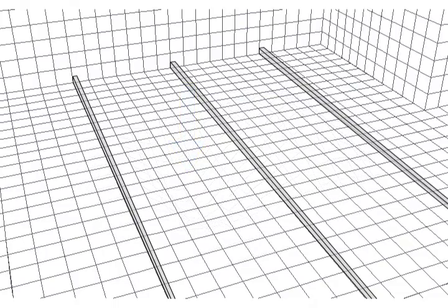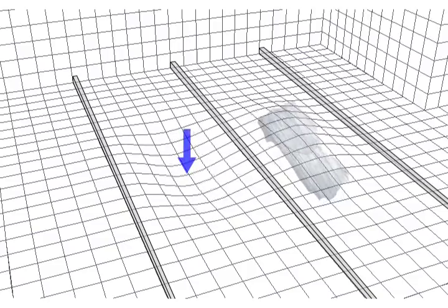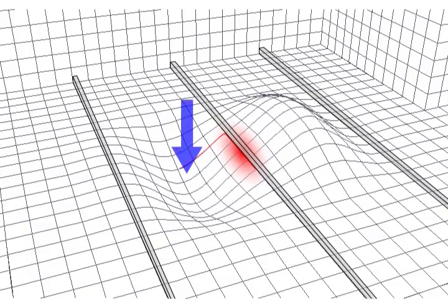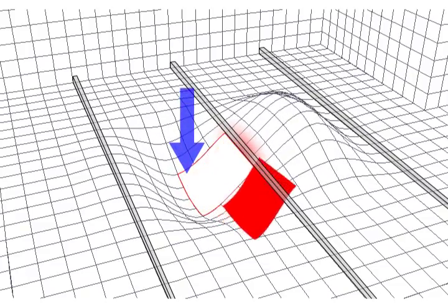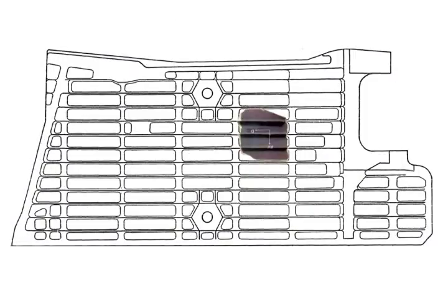When both processes occur simultaneously, the increasing area of strain and increasing outward pressure eventually leads to the weakened area fracturing outward. This results in partial or complete release of the tank bottom section, as observed by examination of the No. 5 fuel tank panel recovered from Runway 26. Investigators also concluded that an additional pressure increase may have come from small, high-speed fragments that may have penetrated the tank surface and contributed to the overall internal pressure increase.